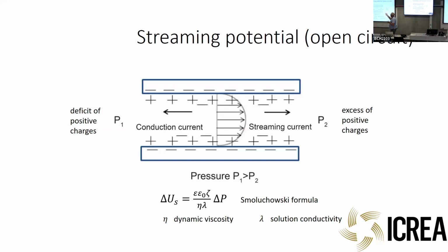the magnitude of this conduction current is controlled by the conductivity of the liquid. If the pore is large, this is the conductivity of bulk solution. And this gives rise to a formula famous in our communities, which dates back more than 100 years, which shows here the so-called zeta potential, viscosity, and lambda, the solution conductivity. And as long as the pore is large, it's bulk conductivity.